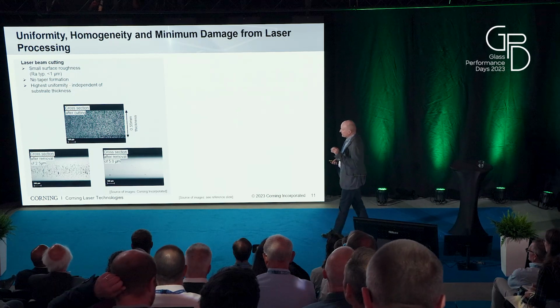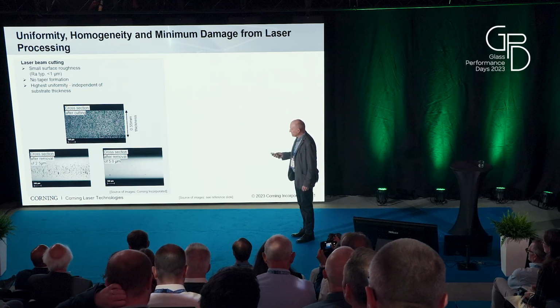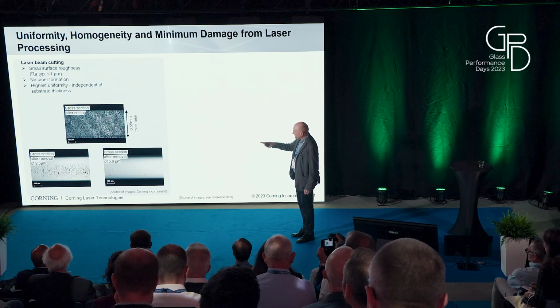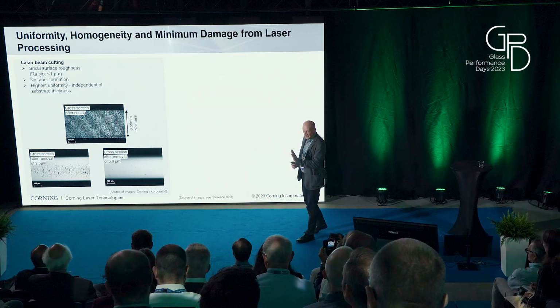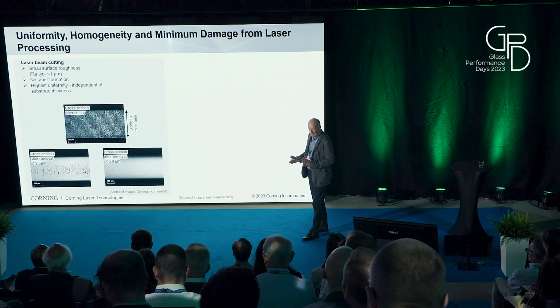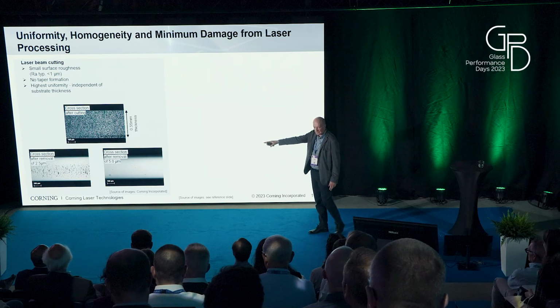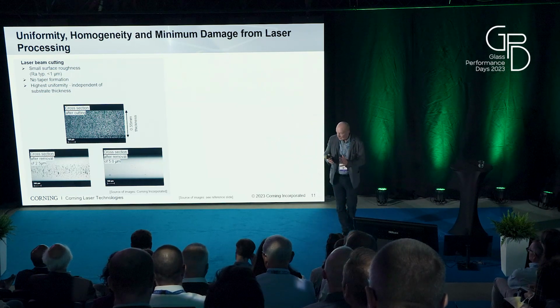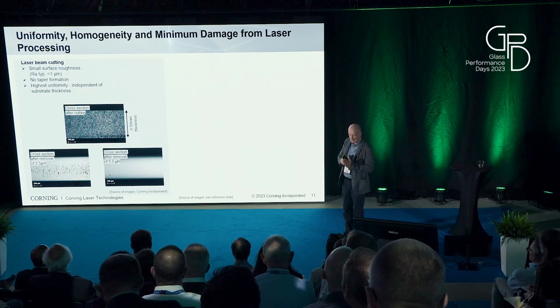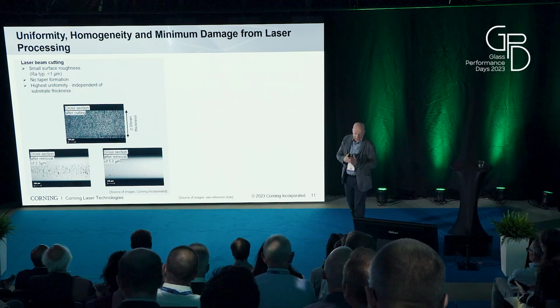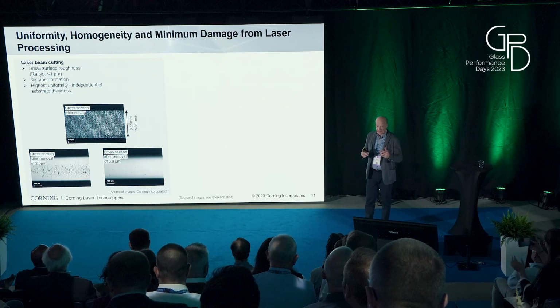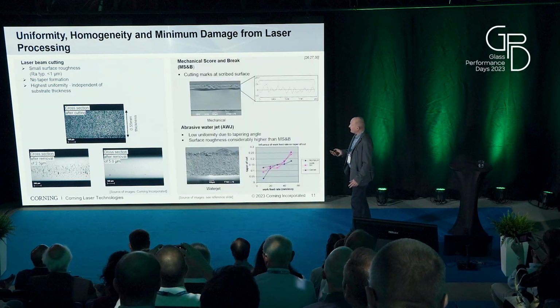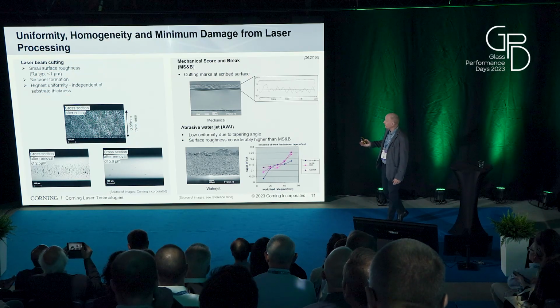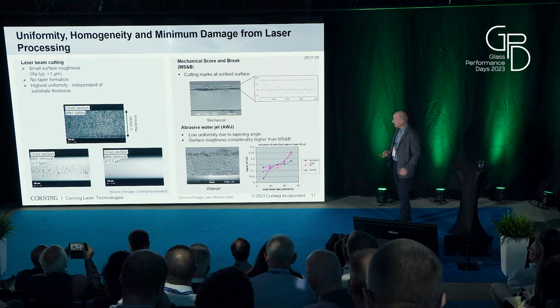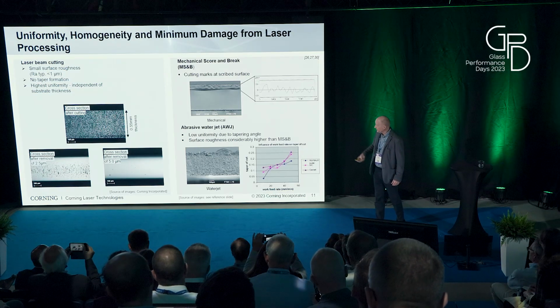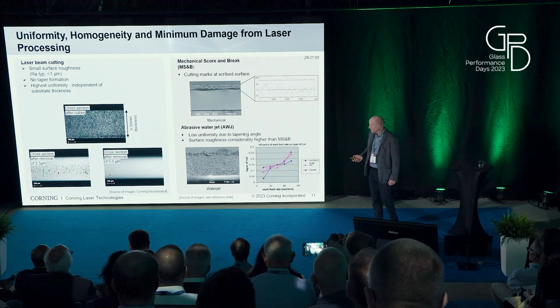It's also interesting that they zoom into the edge surface, and then very interesting here the lower two pictures, where we removed just a little bit of material. This was done by etching, and what you see here is that when you remove only 5 microns of the material, you practically don't have any subsurface damage anymore. And this is essentially one of the reasons, if not the main reason, for the high edge strength. So it's not only the good chipping. And this looks, of course, different with cone break, where we have the cutting marks from the scribe wheel, or then even worse with the surface cut with a water jet.